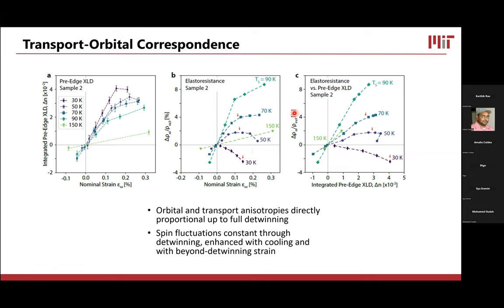If you plot the resistivity versus the XLD, then you get a plot that looks like this. If we're at the nematic transition, there is a very large slope. So the resistivity seems to change very strongly with the orbital polarization. But as we get colder below the nematic transition, we see this slope starts to drop off and it eventually goes negative. So this lines up with the sign change in the elastoresistivity that we saw earlier in the introduction. So why would that happen? These red arrows are showing the point where the sample is fully detwinned.